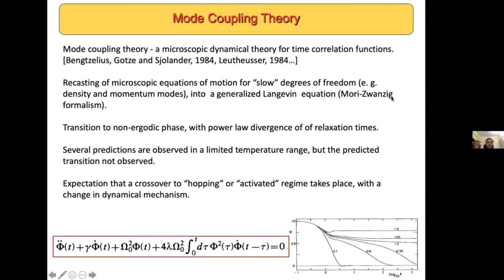This is not their work. This is something that's standard, that goes by the name of the Mori-Zwanzig formalism. This can be done, but the separation of slow and fast degrees of freedom is dependent on the system one is looking at. So what mode coupling theory did was to write down an explicit expression for the memory kernel that appears in these generalized Langevin equations in terms of the correlations or products of the correlations themselves, which leads to coupling of density fluctuations at different wavelengths. And this nonlinear feedback leads to a transition to a non-ergodic phase with a power law divergence of the relaxation times.